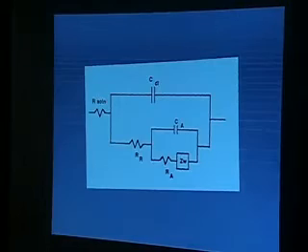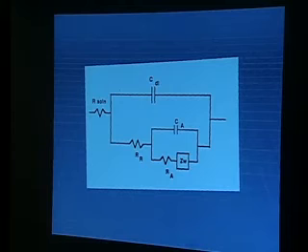Okay, so let's take this to a, you can get really exciting now with these circuits you see. So the problem that I've been trying to model all of these techniques on has been this nickel ferricyanide electrode, you will recall. And so let's go back to that electrode system. And you remember that in that system we have an ion current, essentially. That is, we're pumping ions in and out of that thin nickel ferricyanide on nickel layer. And I had argued that there was an effective viscosity for the nickel ferricyanide layer, and therefore we had this time-dependent diffusion coefficient when we do a chronoamperometry experiment, because not only are we pumping ions in and out of the surface when we do a potential step, but we're changing the dimensions of the crystal structure simultaneously, and that changes the flow ability of the ions through that structure.